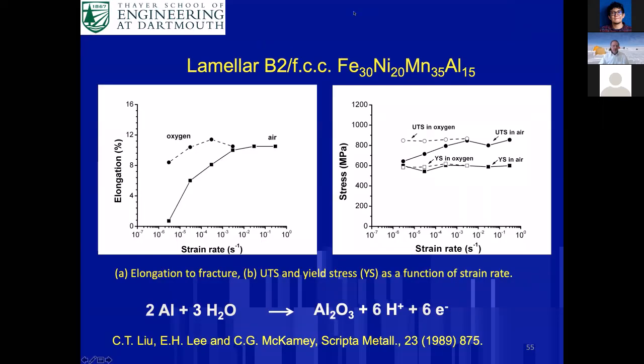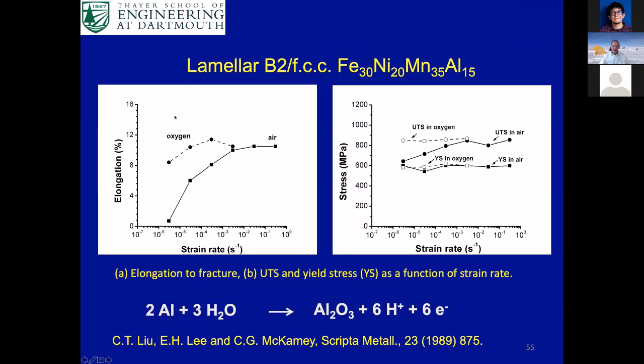So one of the very interesting things about this is when we do tensile testing, if you look at the yield strength as a function of strain rate, there's no effect of strain rate on the yield strength, but there's a really dramatic effect on the ductility. So at high strain rates, you can get about 10% elongation. As you go down to a slow strain rate, the ductility decreases, so you can only get about 1% elongation. And the reason for this is likely to be this mechanism first suggested by C.T.